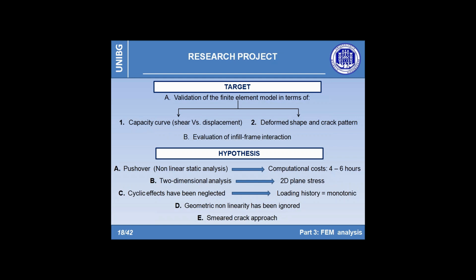The numerical simulation takes into account only the material nonlinearity by means of a smeared crack approach, while the geometric ones have been neglected. Moreover, for the sake of simplicity, only monotonic pushover analyses have been performed, reducing also the computational cost to about 4 to 6 hours. In this way, the damage accumulation due to the cyclic actions has been ignored.